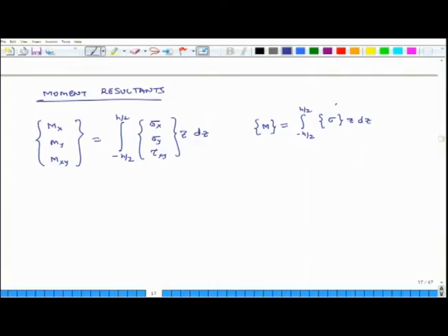But the stress vector sigma is what? It is the Q bar matrix for each layer. If I have to compute it at any layer, it is Q times strain. And what is strain? It is mid plane strain plus z times curvature.